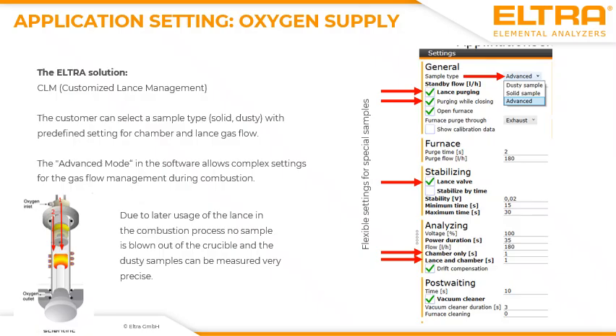And here we will find the suitable application settings for the Elementrac CS, which are located in the application settings. Which means, when you have in mind the table we discussed before, when you apply the settings for a dusty sample, we have an automated setting for the lens and for the chamber so that the sample is first combusted with the stream of oxygen applied through the chamber, followed by the application of oxygen by the lens. So this is a good interaction between these oxygen streams so that no powdered sample is blown out of the furnace.